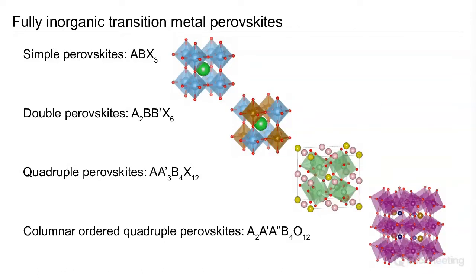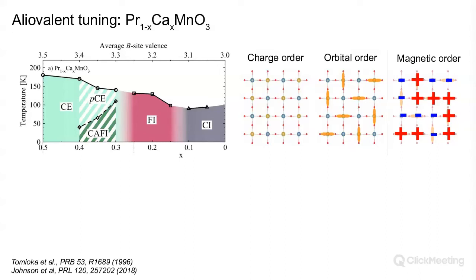Okay, so I just wanted to introduce some interesting concepts that appear, with a particular focus on magnetism. One of the things that one can do with this framework is aliovalent tuning. So we can mix a 3+ cation, for example, praseodymium here, and a 2+ cation, calcium, at the A site. And in doing so, we can tune the oxidation state of manganese at the B site. And then these really extensive phase diagrams appear, which are incredibly rich as far as the magnetism is concerned.